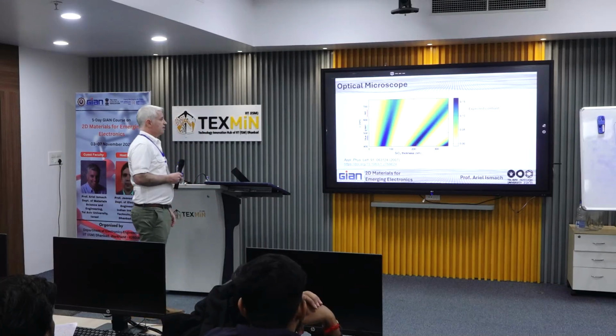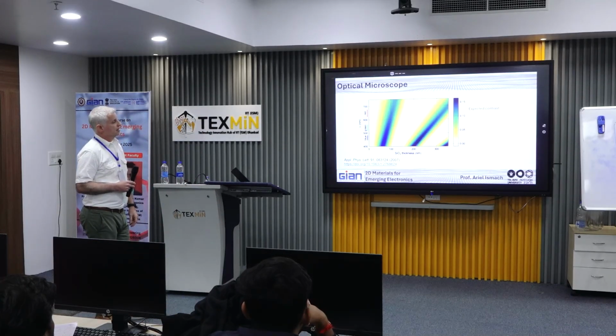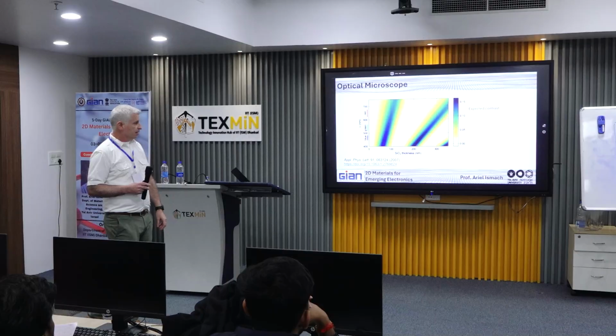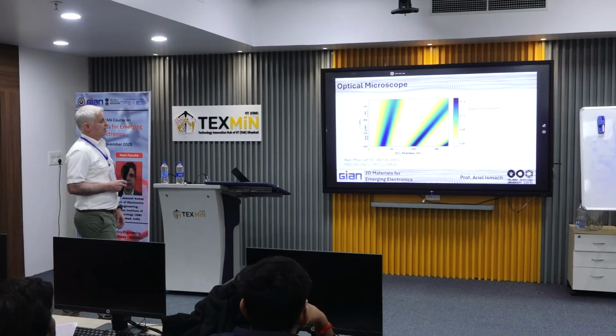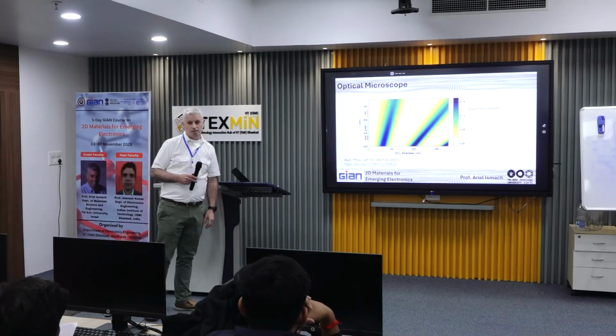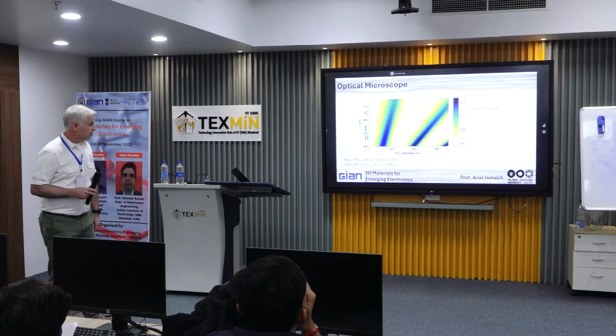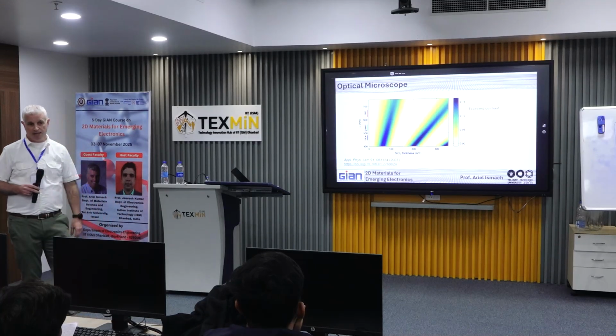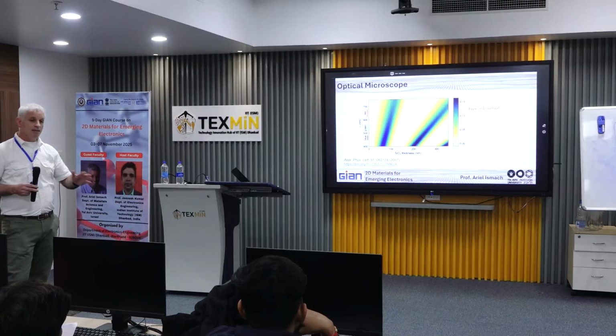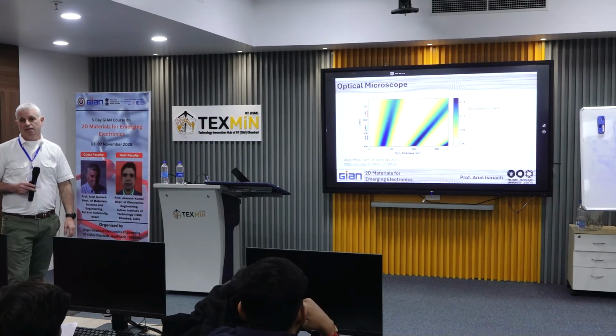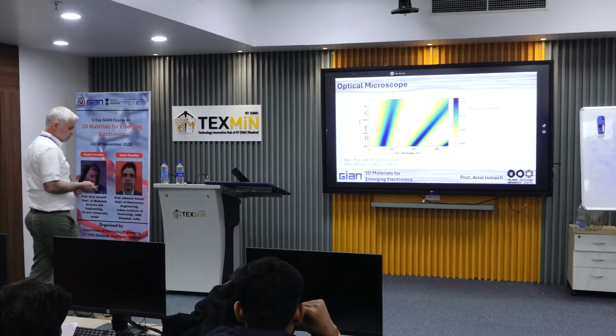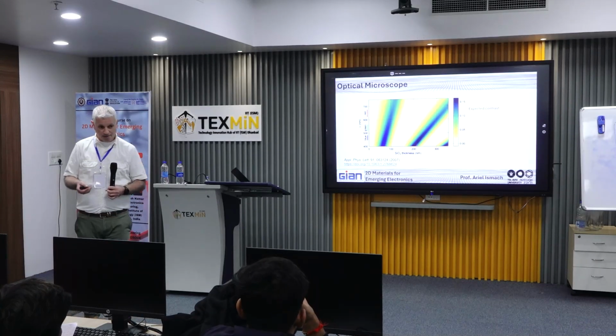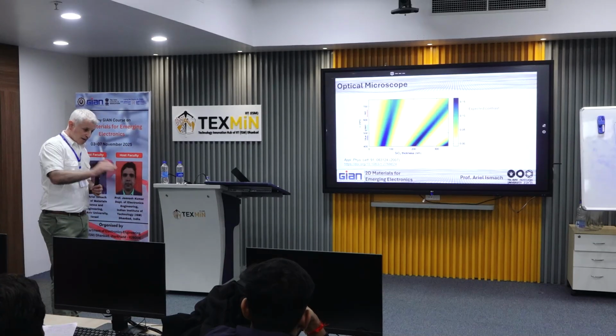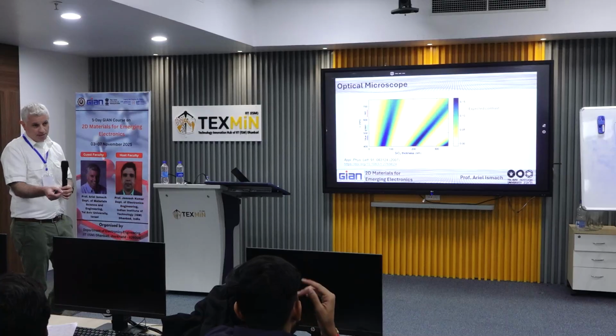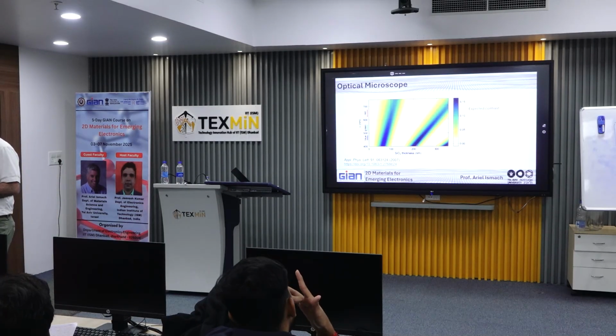So that means that we need something like 285 to 300 nanometers thickness of silicon dioxide, or 90 or 100 nanometers of silicon dioxide. If you do it on a different thickness, like 150 nanometers of silicon dioxide, the single layers will be very, very hard to notice. So here you have a very simple tool that, right after the exfoliation, you can use to check immediately if you have the material that you're looking for.